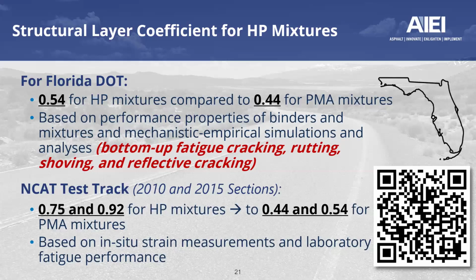For example, the Florida DOT recommendation was to use a 0.54 structural layer coefficient compared to a typical 0.44 for PMA. This was developed based on performance properties of the binder and the mixtures, using mechanistic-empirical simulations and analysis, taking into consideration several critical distresses such as bottom-up fatigue cracking, rutting, shoving, and reflective cracking.